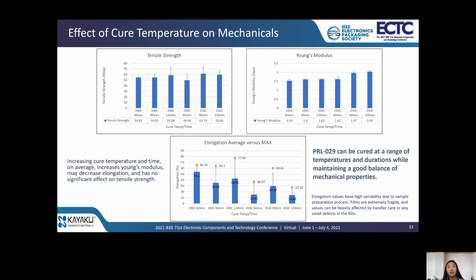Based on our results, we can conclude that there is no significant effect on tensile strength, and that the Young's modulus slightly increases from 1.6 gigapascals to around 2 gigapascals above 250 degrees C for a 90-minute cure. As we discussed in the previous slide, the elongation values have high variability. In the bottom chart, the blue bars are the average of the samples, with an average sample size of around 5 test specimens. The orange dot above the blue bar is the maximum elongation value achieved per sample set. So it's really difficult to make a conclusion from the results as the deviation is quite high. However, we can maybe say that the elongation decreases with increasing temperature from 200 degrees C to 250 degrees C. Overall, PRL-29 is capable of being cured at a wide range of temperatures and durations while maintaining a good balance of mechanical properties.